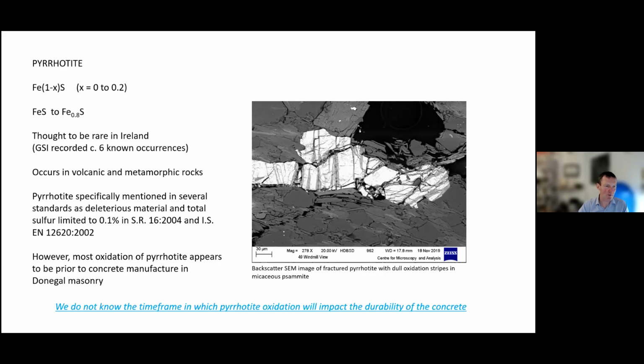And in cases where pyrrhotite is found, the total sulfur of the aggregate is limited to 0.1%. This is in the standard SR16 aggregates for concrete and the European standard that supports this. So it shouldn't be used as aggregate if the sulfur is more than 0.1%. However, and this is a big however, most of the oxidation of the pyrrhotite that we have observed, and this is several labs, not just myself, most of the oxidation appears to be prior to concrete manufacture. So it's oxidized and then it's been incorporated in the block. And unfortunately, we do not know the time frame in which pyrrhotite oxidation will impact the durability of the concrete. And this is an area that really requires research. So I'll come back to this towards the end.